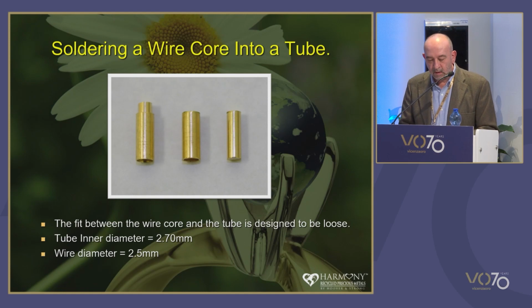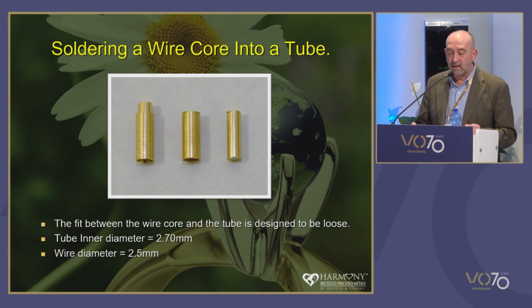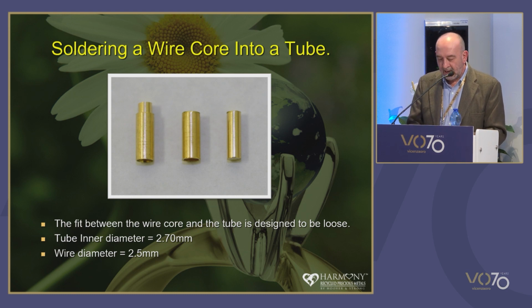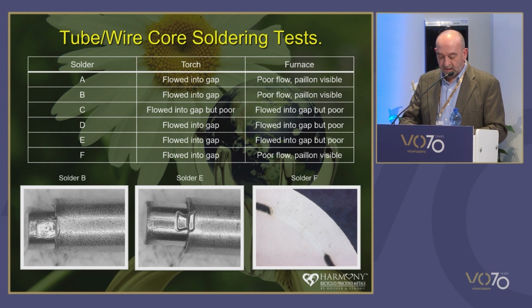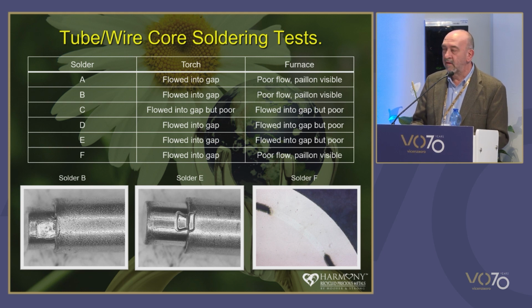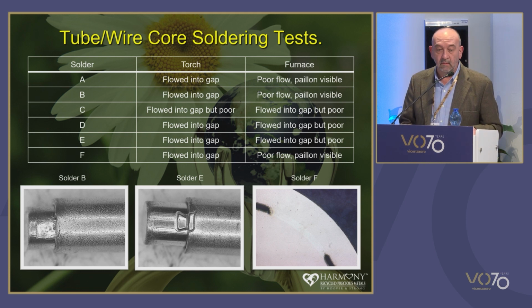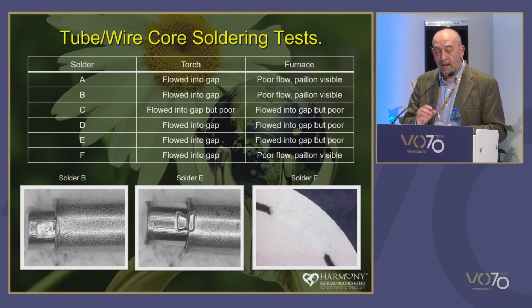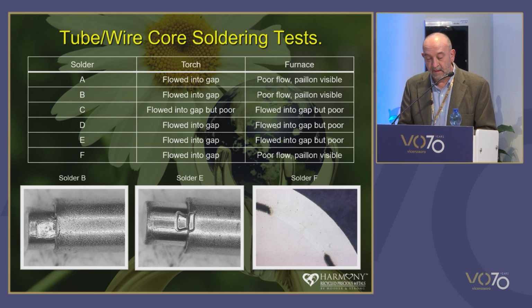So the final test we did was to put a core and solder it into a tube. As we can see the pieces here, we designed it to be a loose fit. So we had a tube with an ID of 2.7 millimeters, and a wire diameter of a very loose fitting 2.5 millimeters. And these are the results. I'm not really going to go into these a lot here because the test was not very good. It was a badly designed test. All it really showed us was if the gap's too big, then soldering doesn't work very well. As you can see from the microsection on the right, there's lots of voids in there. And again, we see with the white solder in the middle and solder B, we have that residual piece of solder still evident in there.